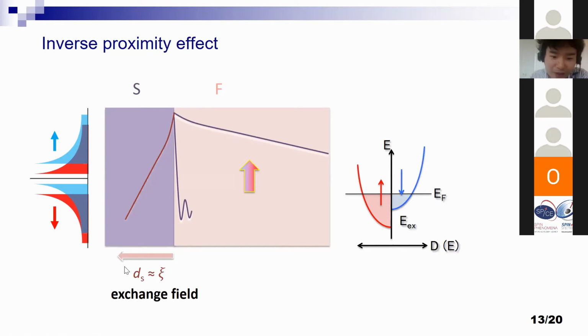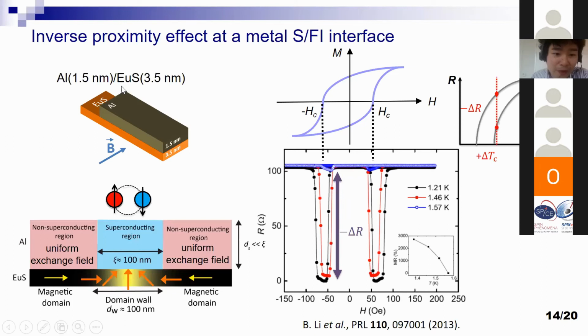And we can detect this inverse proximity effect from a simple transport measurement, for example, a bilayer of aluminum and europium sulfide, so a superconductor and ferromagnetic insulator bilayer structure. An important thing is to match the length scale of the coherence length, the diameter of Cooper pairs, and the domain wall width of the ferromagnetic insulator. If you match these two length scales, what you can see is, in a domain wall region, of course the exchange field is rotating, and if it is on a length scale of the coherence length, basically Cooper pairs can experience an averaged exchange field. So if it is rotating, the effective exchange field here is reduced.